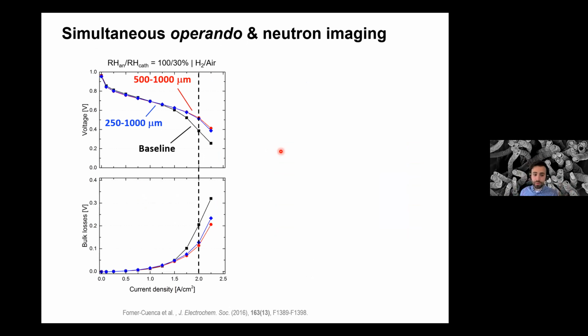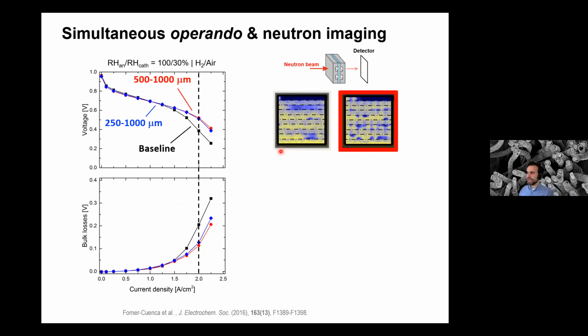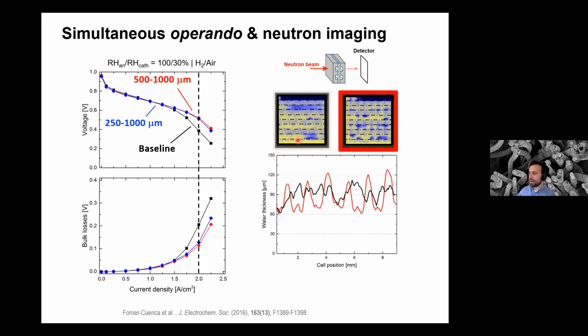And we couple that with in situ performance. So we build that in the beam line. You can put your fuel cell and you can look at it and you can quantify. So it's not only qualitative, but you can quantify local water compositions or saturations in the porous media as a function of the operating condition. And here I'm showing you an example at 2 amps per square centimeter, where we compare a baseline material in black with a material that has pattern wettability in red.